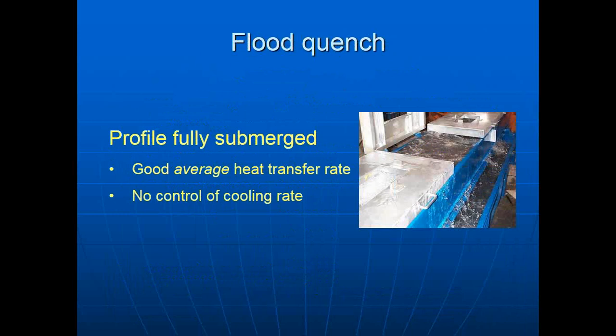Moving up from spray is the flood quench. This comes in the water wall style, where the profile flows into and out of a standing wave of water, and also the dip quench, where the entire profile is dipped in a trough located typically next to the lead out. So the profile, after it's produced, is dipped in its entirety into the trough and removed.